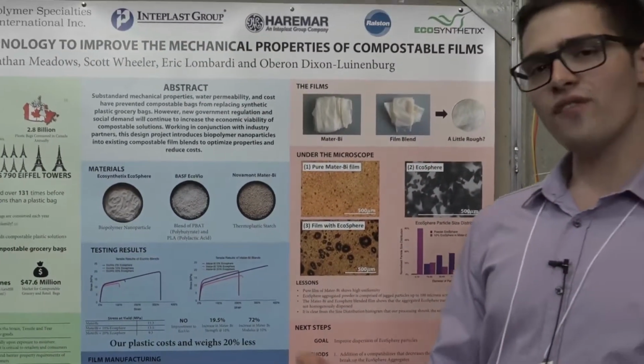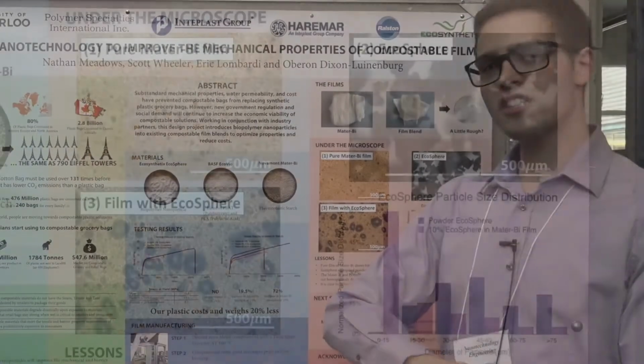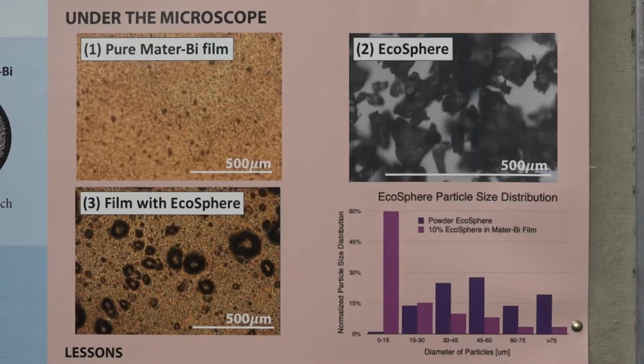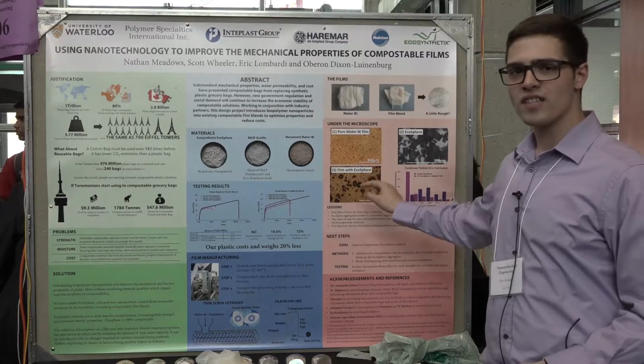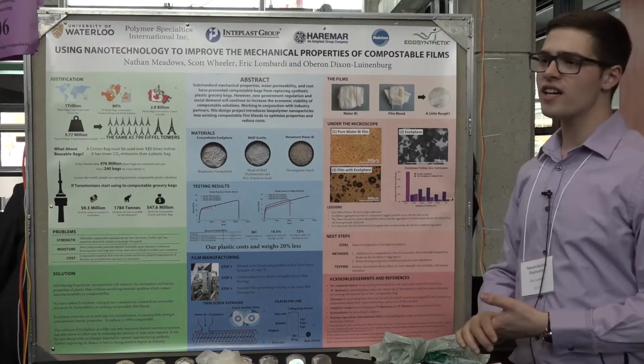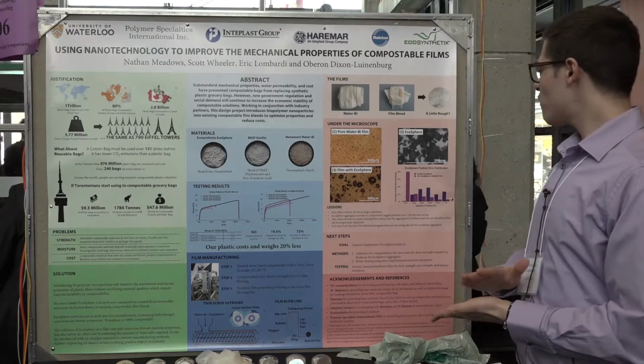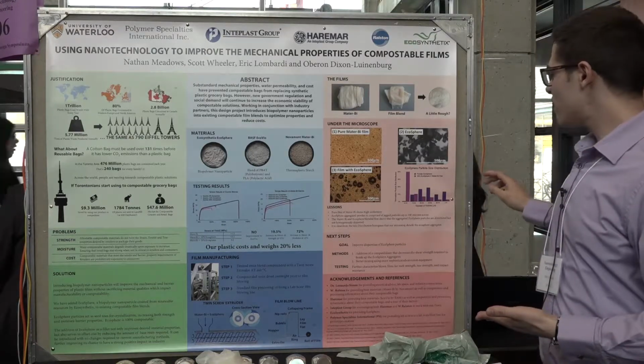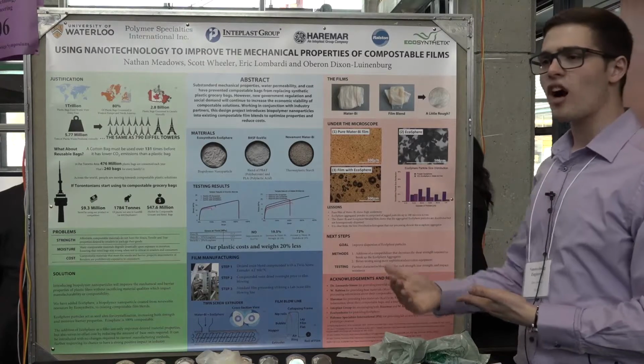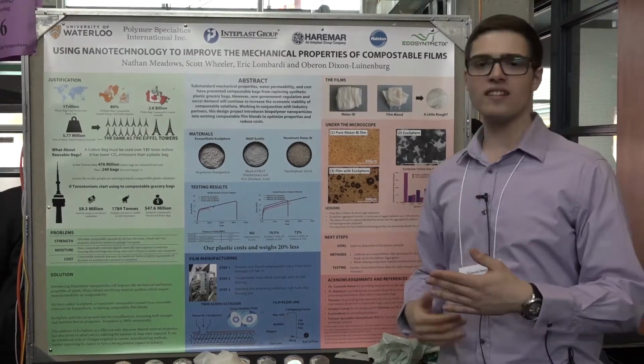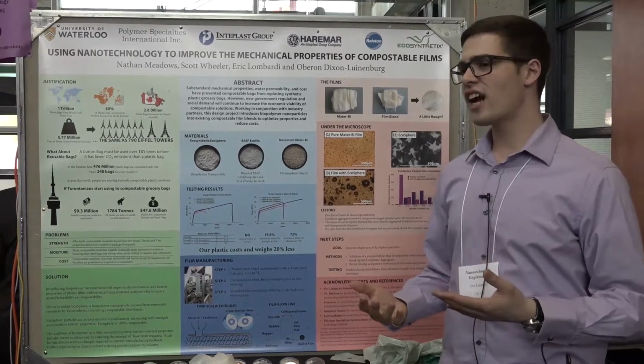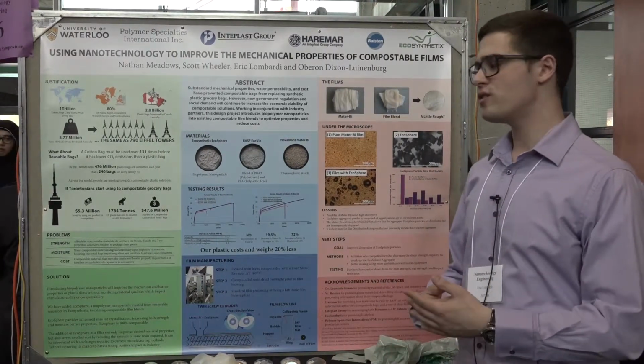One of the things you can see in our film, however, is the presence of aggregates that are distributed along it. And one of the issues we noticed is, well, why is this problem occurring? So we did an analysis under the microscope, and we found that while our EcoSphere particles were deaggregating, they were not deaggregating enough because there was not enough requisite shear strength in the extruder that we were using in order to fully break them up. So upon further investigation, we found that the next improvements we would make are in processing. And this would require equipment that does not currently exist in Southern Ontario and would cost about $300,000 to produce.